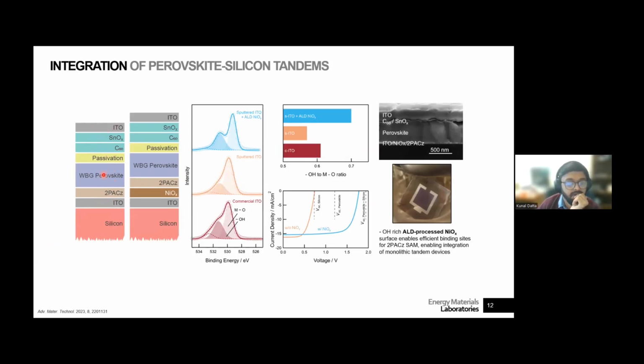But what we saw was that it wasn't as straightforward to integrate, so just kind of build up, because what became critical was this interface between the ITO and the 2PACz, right? Because the ITO that was being used in the single junctions was something that we buy commercially. So the surface is significantly different than what we can process in our own lab when we sputter it instead. And that we looked at with XPS.